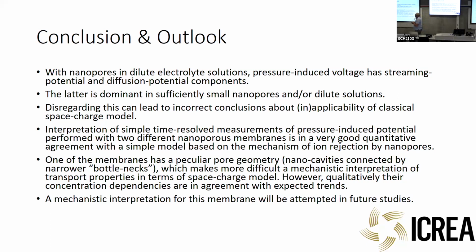So we have demonstrated this for two kinds of membranes, straight-edged with cylindrical pores, and also other membranes. Well, this is very recent, so we did not have time yet to do mechanistic interpretation, but this is on the way. So maybe next time I will be able to tell you about this membrane, which actually is a very interesting material in terms of practical application, extremely stable, polyimide, stable up to 200 centigrades, organic solvents, acids, bases, so extremely interesting material.